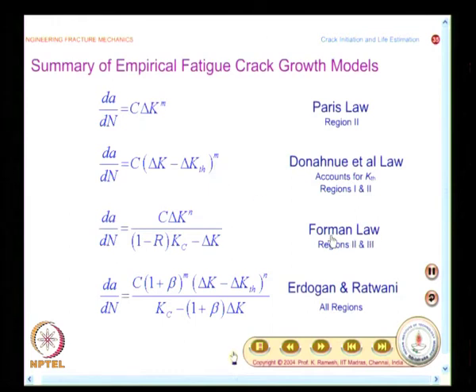Then you have the Forman law. We saw that a variation of Forman law is used in advanced software for crack growth calculation. This accounts for region 2 and region 3 better. And you have dA/dN equal to C delta K power n divided by (1 minus R) multiplied by (K c minus delta K). Then you have dA/dN equal to C into (1 plus beta) power m multiplied by (delta K minus delta K threshold) whole power n divided by (K c minus (1 plus beta) multiplied by delta K). This accounts for region 1, region 2 and region 3. This is by Erdogan and Ratwani. So, these are all the variations of basic Paris law to account for different regions. Then we will also look at how this could be modified for different effects.